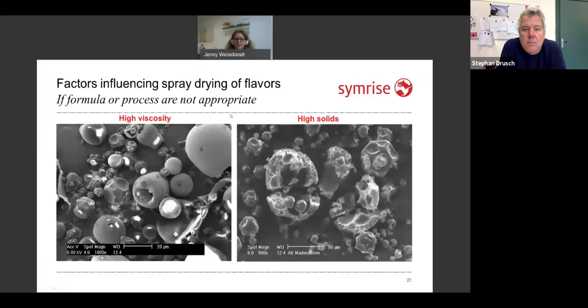And now you can see what happens if your viscosity is too high, or if you use too much solids and dry too fast. You see here that you have very thin shells of the capsules. So what has happened? It was a very high viscosity. The capsule surface, or the droplet surface, dried, densified, and the water wasn't able to move out. And then it happens what I said before. The water vapor develops in the center of the particle. It didn't come out, and then it led to a particle burst. And then you see this here, it's a disaster area.